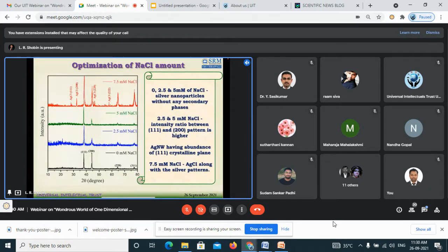What I'm doing is increasing my sodium chloride concentration. If you see over here, when 0 molar, I mean no NaCl is added, it started producing particles. But if you go for a higher concentration, for example greater than 5 millimolar, I am able to see AgCl crystals also inside the system. So we found that 5 millimolar is sufficient for the preparation, and they are all abundant in a (111) plane actually.